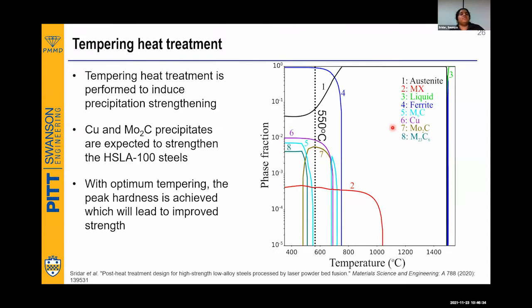But this is not sufficient. So the next step is to do a tempering heat treatment to induce strength. Why? Because I had already mentioned that copper is going to induce precipitation strengthening, and similarly, the addition of molybdenum is to induce the Mo2C precipitates. So in order to induce the precipitation strengthening, you have to temper it. That is, you identify a particular tempering temperature.